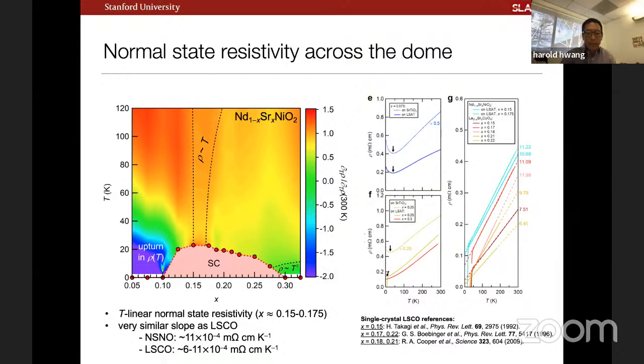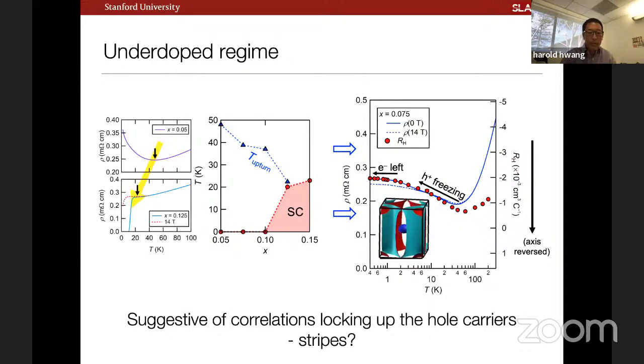So let me spend a slide more on the underdoped regime. It's rather interesting. I told you that this upturn feature seems fairly robust to the disorder, or the variations in disorder induced between substrates. So here's x equals 0.05. This is just entering the superconducting dome, but you can still see, upon suppressing superconductivity by magnetic field, that we can plot this resistive upturn. It's really coming down as you enter the superconducting dome.